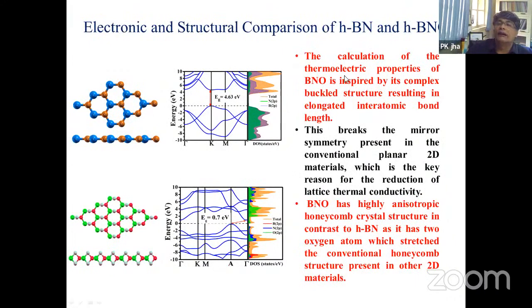This is for the band structure. You can see the hexagonal boron nitride has a band gap of 4.63 electron volt, while the hexagonal boron nitride oxide has a band gap of 0.7 electron volt. And of course, then the chemical potential, the relaxation time, and other parameters are also important, which can be tuned through the band structure. And here the band structure is being tuned. Another aspect for the BNO is what? That it is highly anisotropic, right?